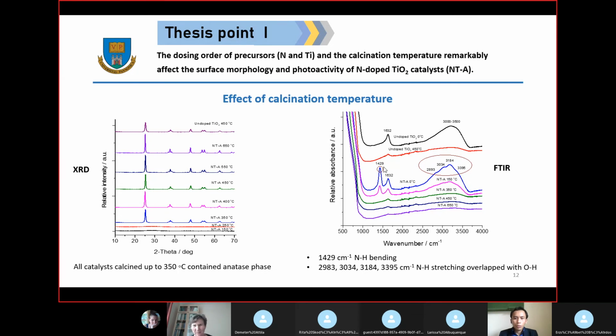The first one is at around 1,400. This is a new peak. This is the undoped titanium, but after nitrogen doping a new peak appeared here. And the second one is around 3,000 per centimeter. So these two peaks indicate the NH bending. In this case, the one at 1,400 is NH bending, and the one here is overlapping with the hydroxyl group.